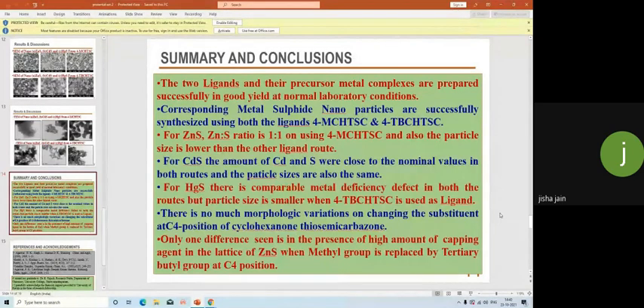For mercury sulfide, there is a comparable metal deficiency defect in both routes, but the particle size is smaller when 4-tertiary butyl cyclohexanone thiosemicarbazone is used as ligand. There are not many morphological variations on changing the substituent position of cyclohexanone thiosemicarbazone. The only difference seen is the presence of a high amount of capping agent in the lattice of zinc sulfide when the methyl group is replaced by a tertiary butyl group at the C4 position.